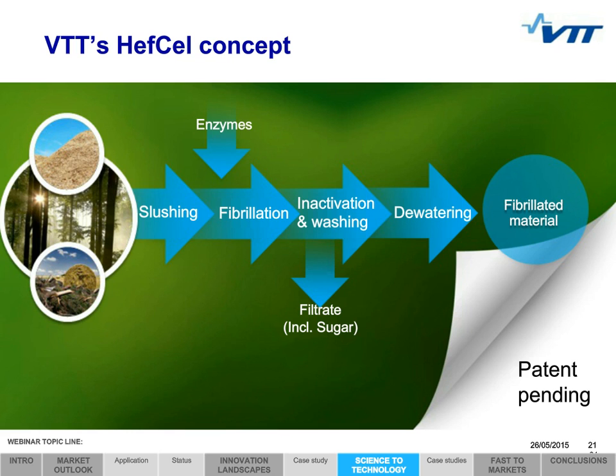After dewatering, the resulting fibrillated material is at high consistency, between 20 to 40%, which is a remarkable increase compared to the concentration of cellulose nanofibril suspensions obtained from traditional processing methods, with around 2%.